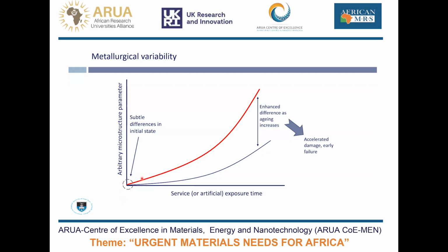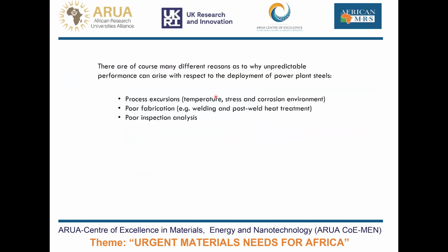But in service, that microstructure might now change quite differently to what might be expected because of the subtle difference in the initial state. And that may well become exaggerated. The difference between these curves gets greater and greater with time. And as a result, this enhanced difference as aging increases leads to accelerated damage or early failure. So that is the complexity of what can happen to these rather sophisticated materials used in power plants.